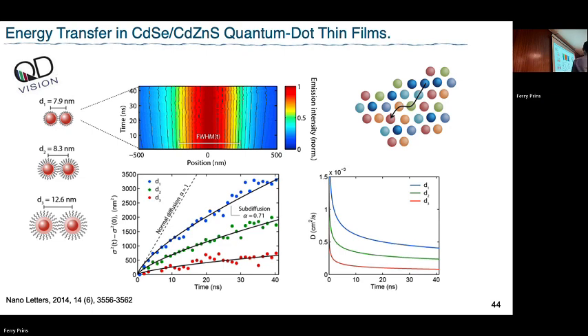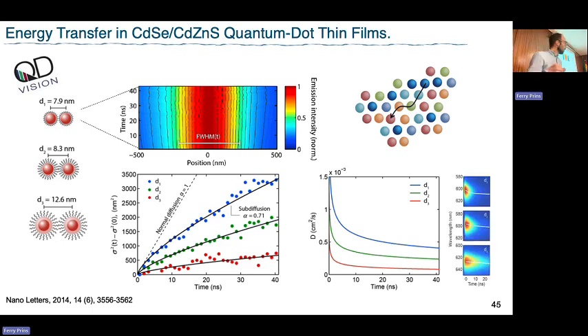This picture is very important, especially in quantum dots. I can tell you this as a hypothesis, but you can measure this too. So here, plotted quite small, you see this spectrum as a function of time, showing the same thing: there's a redshift in the spectrum, and that redshift coincides with the slowing down of your transport.